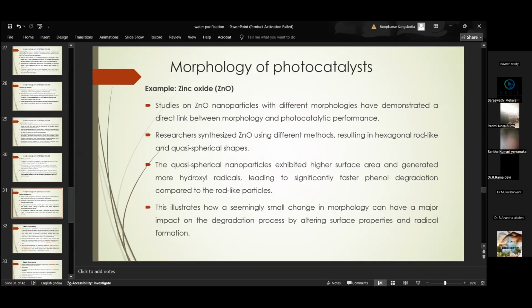The quasi-spherical nanoparticles exhibited higher surface area and generated more hydroxyl radicals, leading to significantly faster phenol degradation compared to the rod-like particles. This illustrates how a seemingly small change in morphology can have a major impact on the degradation process by altering surface properties and radical formation.